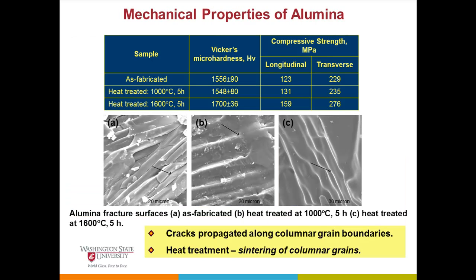If you look at the mechanical properties, the as-fabricated one has a pretty high hardness, 1556. That's what we typically get, but there's definitely a sensitivity between longitudinal and transverse direction. Longitudinal is almost half, because these are compression testing. When you do compression testing, the crack pushes, so the longitudinal columnar grains are actually a weakness, giving almost half the strength value for longitudinal compared to transverse direction.